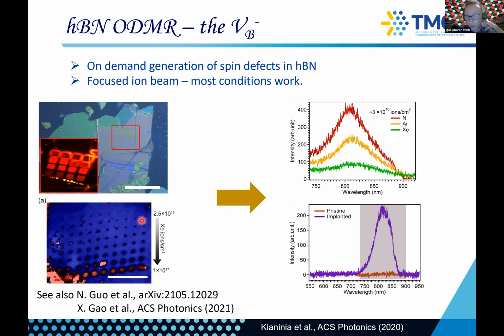It's so dim that when you image here at the very dim sites with the hope of finding a single photon source, you actually do not see anything. So we still, after all these many attempts, haven't seen a single VB defect. And I will show you how we try to go about it. But nevertheless, so far, that's the only defect in hBN that we actually know what it is. In the first part of my talk, when I discussed the single photon sources, we don't actually know what they are. We have a good guess that it's carbon related, and we can create them very easily and very bright, but we don't know what they are exactly. With this defect, it's the other way around. We know what it is, but we cannot get a single.